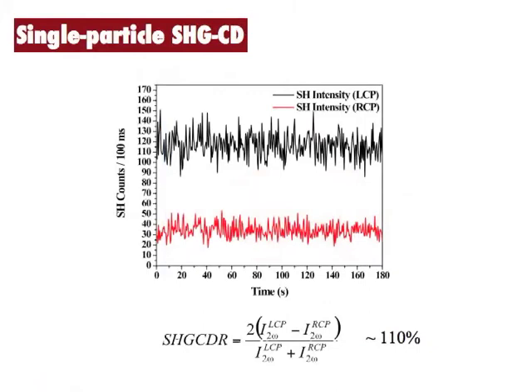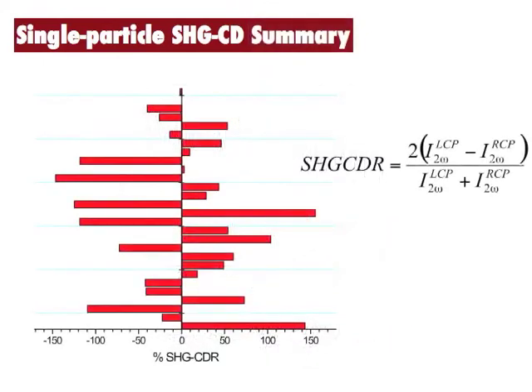One of the examples we describe in the perspective is the amplification of circularly polarized light, producing chiral fields. This effect is summarized here, where the SHG intensity resulting from left and right circularly polarized fundamental light is plotted. These data can be analyzed using the equation shown here to quantify the circular dichroism present in the nonlinear optical signals. We learned that the degree of circular dichroism detected is very sensitive to the nanoantenna structure. This plot illustrates the unique results obtained from several different nanoparticle assemblies, an effect that would have been washed out by ensemble averaging.